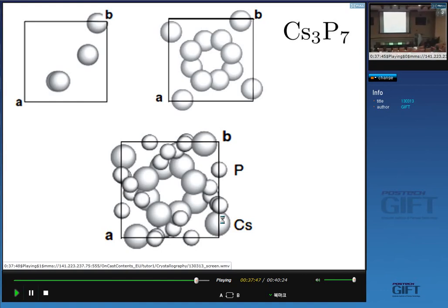So if you didn't have your space group table, this would be really complicated, because the location of the atoms is not a nice number, like half, half, half. Yeah? So in this example, we build the structure by knowing the space group. Okay? If you've got the correct space group to start with, then your structure will be correct. And the only way to check that is you do your diffraction experiment. You measure the density of the cell. If you've got X number of atoms inside the cell and you know the cell dimensions, then the density must come out correct. And various other experiments to prove that you've chosen the correct space group. Okay?